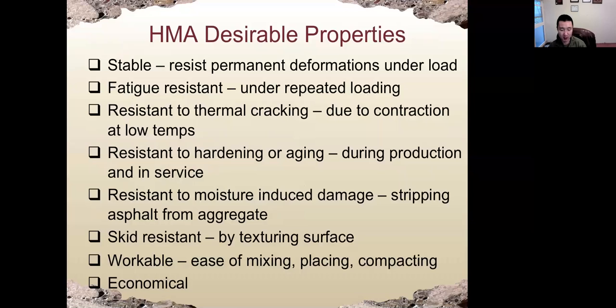The desired properties for hot mix asphalt concrete pavement are stability, which means it needs to resist permanent deformation under load, and also fatigue resistance. The road will be under repeated loading, so fatigue resistance is very, very important. And also resistance to thermal cracking, because when we have temperature change, it will contract or expand based on temperature. It's easy to crack at low temperature, because at low temperature it becomes more rigid. And also resistance to hardening or aging, both during production and during the service period.